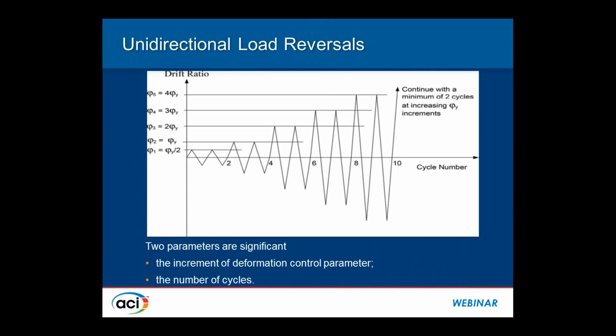cyclic loading. When we talk about reverse cyclic loading, often we test specimens in a unidirectional manner, and the control parameter that I was talking about in this case corresponds to yield drift, and the first two cycles are the elastic cycles. These are the cycles that can be done in the force control mode, and then followed by the deformation control mode at yield, 2 times yield, 3 times yield, until we experience significant strength decay.